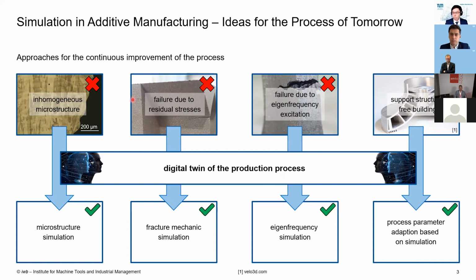So, for example, the failure due to residual stresses when we use a fracture mechanics simulation, the failure due to eigenfrequency excitation by using eigenfrequency simulation, and also the support structure free building, which should be addressed by simulating different process parameters that can be then adapted based on the simulation results, and then also used to control the real manufacturing process itself. But how can we couple these different simulation tools and features? So therefore, we thought about using a digital twin of the production process. The digital twin should then represent the real manufacturing process with all the pre- and the post-processing steps.